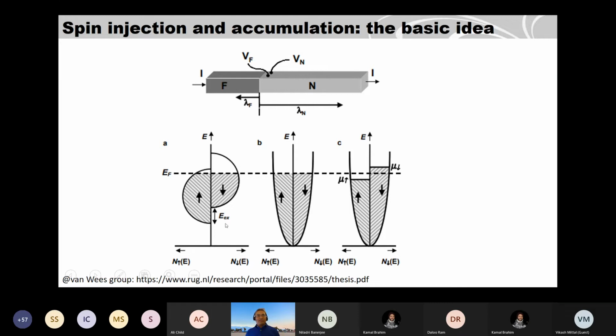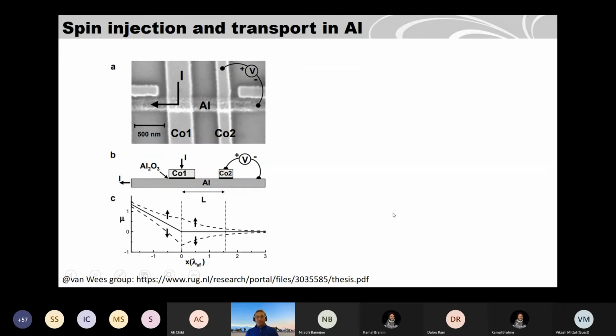So these are the basic things. The ferromagnet has a simplified band structure here. So you have the spin density of states and you have more spin down, for example, at the Fermi level. And this is the density of states for the aluminum. And these are the s electrons here. And you have an equal number of up and down spins. But when you apply an electric bias, or you apply an electric current here, you inject spins from the ferromagnet into the normal metal, and this will be non-equilibrium spin. And what you will do is you create a spin splitting in the band of aluminum close to the interface. So we'll see how long the spins can go in aluminum. But close to the interface, you create a spin splitting between up and down spins. So mu up is the electrochemical potential for the up spins, and mu down is the electrochemical potential for the down spins. So once you do that, you can also detect those spins.